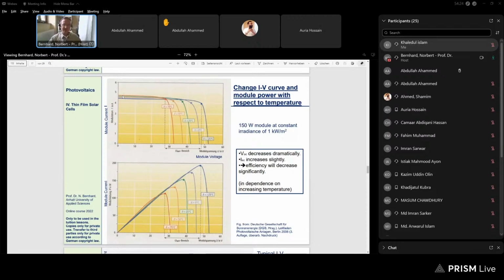Okay, the lower curves are just the power curves. You see the power in dependence on the voltage. And here we see especially clear how the power really changes. You see at minus 25 degrees centigrade, the module has almost twice the power as at 75 degrees centigrade. This is a very significant decrease.